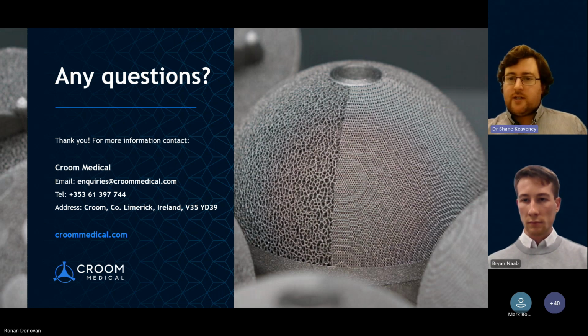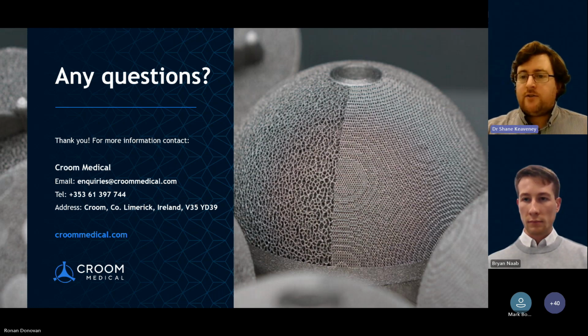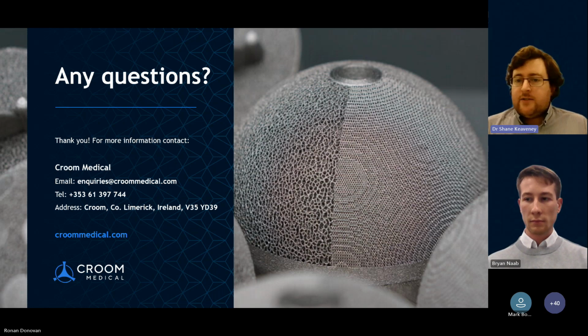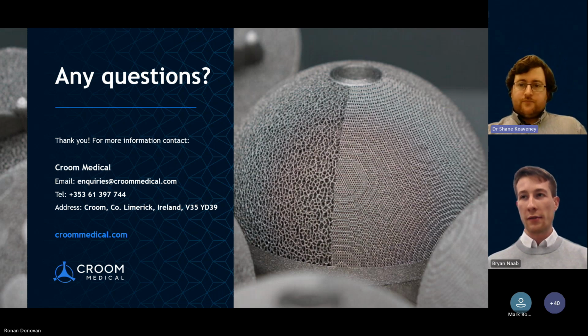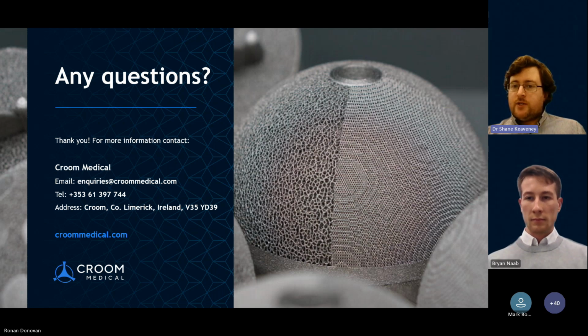Yeah, so Bryan, I'm not sure if you want to take that next question there in terms of ultrasonic cleaning. Some of that obviously we can't share in terms of the detergents and cleaning agents we use, but ultrasonic cleaning is quite a good method for wet powder removal. So if you have any further comments on that one, Bryan. Yeah, I would say specifically when you're talking about really fine lattice structures, you might find ultrasonic cleaning is not a fine enough process to remove those powders. So you might actually have to look into even megasonic cleaning. Yes, if we're dealing with extremely small structures, they would be smaller than what we typically expect for osteointegrative structures. So very good.